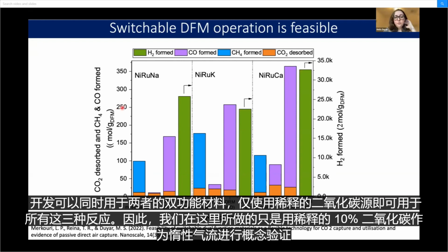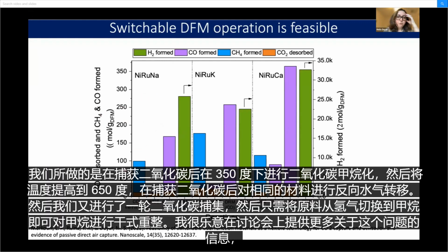So here, what we've done is just a proof of concept with a dilute 10% CO2 in inert gas stream. We performed CO2 methanation at 350 degrees after CO2 capture. And then we raised the temperature to 650 degrees to perform reverse water gas shift on the same material after CO2 capture. And then we performed another round of CO2 capture followed by dry reforming of methane just by switching the feed from hydrogen to methane. And I'm happy to give more information about this during the discussion session.